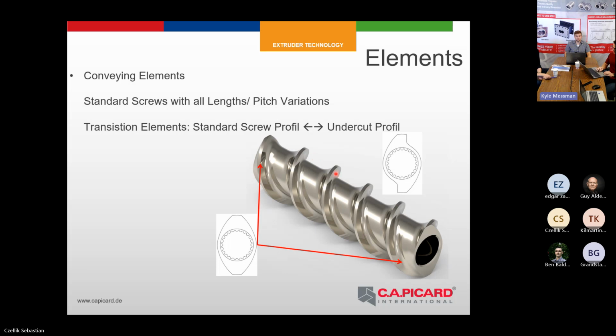If we have these elements as three single-piece elements and you put these elements together, you have, at least on this side, an overlay of these two profiles. So what is the problem with this? If we have an overlay, at the latest at this point, you have an undercut of the profile, and the problem is that your product, the polymer for example, may rest on this place for a couple of times, and it burns. And then the burnt particles will release on this surface and will go into your product and into your melt. And then you have the burnt particles, these little black spots in your product.